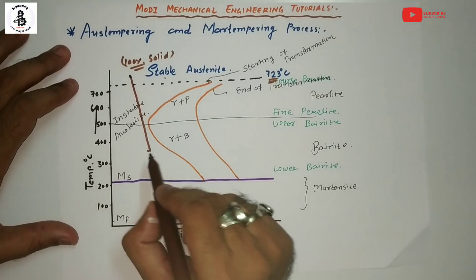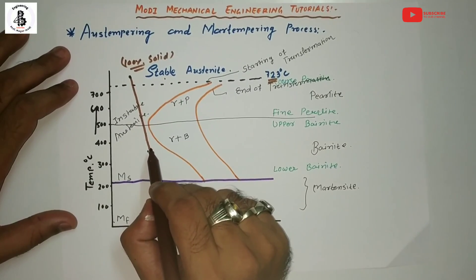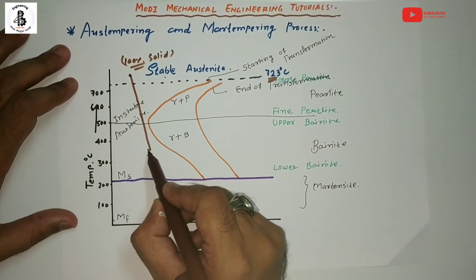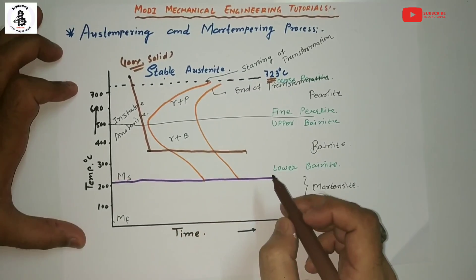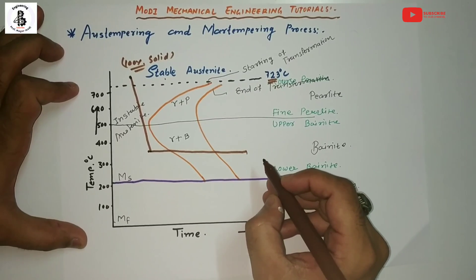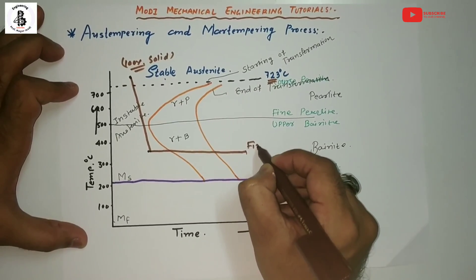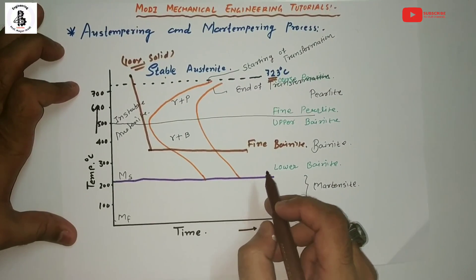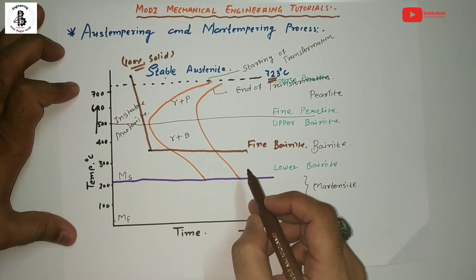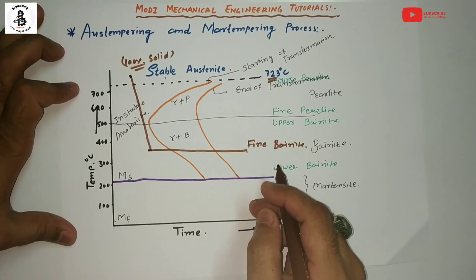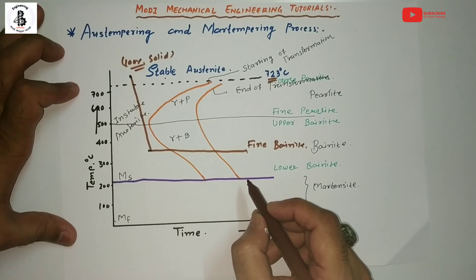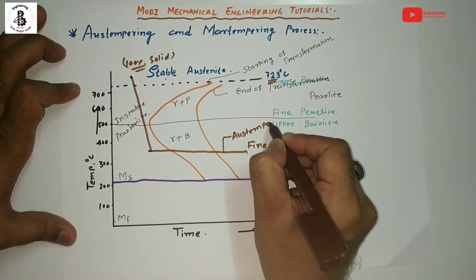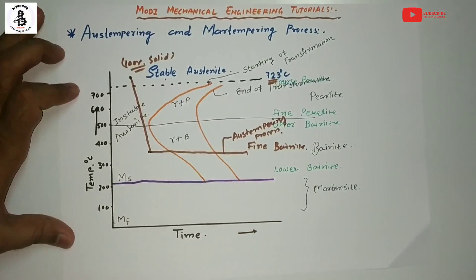The sample is then held at this temperature until the inside and outside temperatures are equal. After that, the part is reheated and cooled at a moderate rate. By this special cooling, the austempering process produces a fine bainitic structure with minimum distortions and minimum residual stresses. Advantages include: quenching cracks are overcome, distortion is avoided, a uniform bainite microstructure is formed with superior mechanical properties.